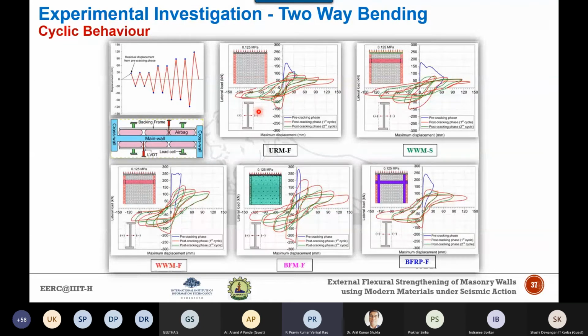This pre-cracking phase, which you can see in blue, has been applied till significant cracking is achieved. Once that significant cracking is achieved, we apply the to and fro action of the airbags in order to develop this hysteretic curve. The pre-cracking phase represents a force-controlled stage in which the pressure in the airbags is gradually increased till the wall depicts a clear cracking pattern, to determine the pre-cracking strength.